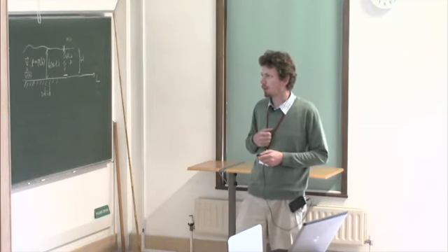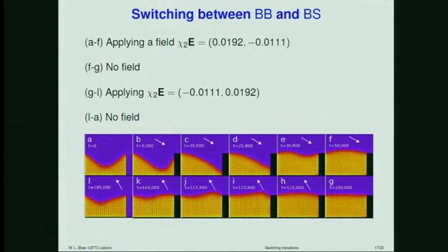And by applying an electric field in the upwards left direction, we can actually reverse this transition, because now this field is opposing the splay configuration in this lower corner and induces the director to rotate until we're back to a bend in both corners.